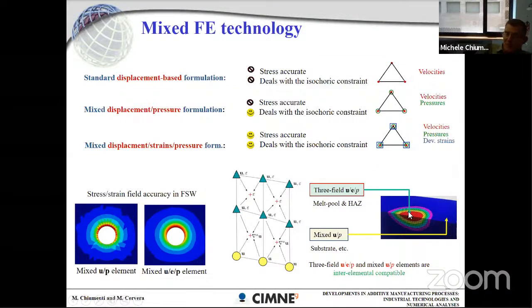This is the case of the melt pool, for instance, or the heat-affected zone, where you have the largest gradient. You can use the three-field formulation where necessary, where you have large gradients, and then you can switch automatically to the UP formulation in any other place. An example is in these figures, which I also presented for friction stir welding. This is a simulation with a very strong gradient close to the pin. Here you can see what you obtain using the UP formulation and what you obtain using the three-field formulation. Completely different accuracy.